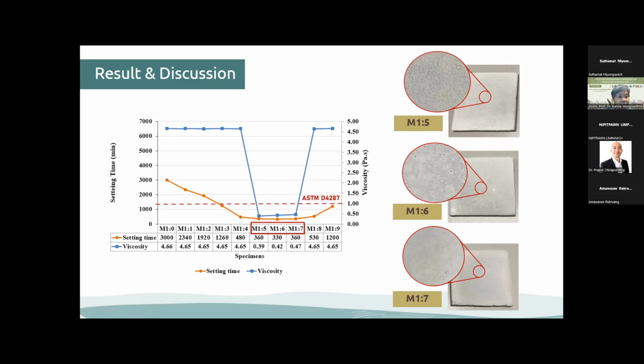The viscosity of the slurry for spray coating should not exceed 1 Pascal second according to the ASTM standard. Our M1.5, M1.6, and M1.7 pass this standard. After M1.8 and M1.9, there was an increase in viscosity due to the increasing silicon per aluminum molar ratio, because of the increasing sodium silicate, and the sodium hydroxide decreasing is insufficient to dissolve the metakaolin.